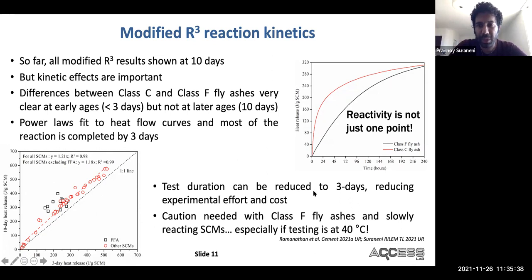And this path is really important because if you look at early ages, the class C fly ash is a lot more reactive than the class F fly ash. In the first 3 days, the differences between these materials are very clear, but it's not so clear at later ages. And this is really interesting because this is exactly how these materials behave in concrete, only at different time frames. In concrete, class C fly ashes react rapidly. They give high strength at about 7 and 28 days. The class F fly ashes react slowly, but they react in a sustained manner. At 91 days, very often the differences in strength between class F and class C fly ashes are minimal.